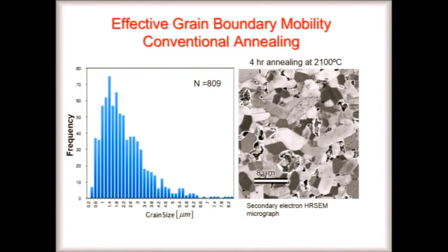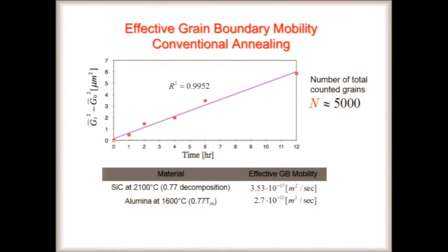This is the conventionally annealed sample, and here you go. This is the same thing that you saw a minute ago with calcium. You have elongated grains. This is intrinsic to silicon carbide doped with carbon and boron. We can measure the grain size. Is this beta or alpha? This is alpha. And we can do this analysis of grain size, and the parabolic fit works. We extracted a grain boundary mobility of 3.53 times 10 to the minus 17 meters squared per second.